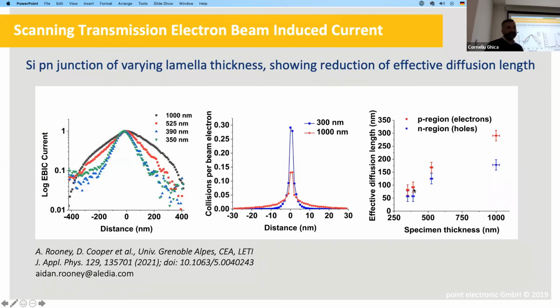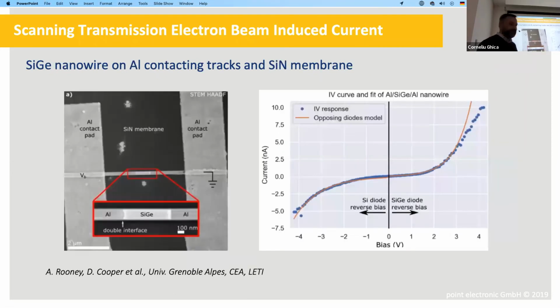And this is an important fundamental physical parameter, the diffusion length. And we can measure that with high resolution. What this is showing us in this particular example is that as the lamella is becoming thicker, the diffusion is also longer. So that means the diffusion of charge carriers is not limited only by purity and the doping of the material, it's also limited by these two surfaces that confine the electrons. So they're not as free to move, or they recombine before they get a chance to move, however you look at it.